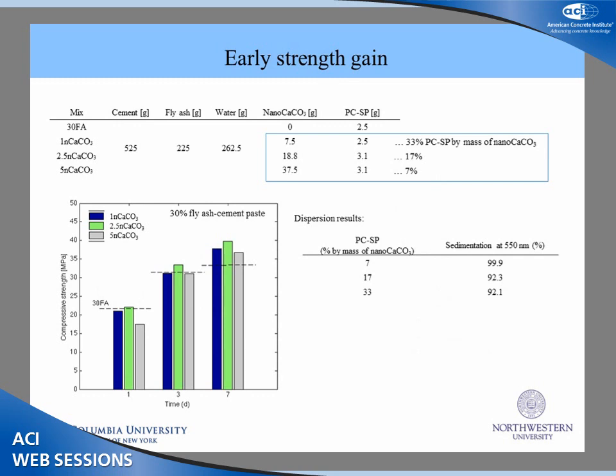Now we also tested early age strength gains, so 1, 3, and 7 day. If you just focus on this plot in the lower left-hand corner, the line indicates just 30% fly ash cement paste with no nanocalcium carbonate. And then the effect of 1, 2.5, and then 5% nanocalcium carbonate addition. And we see that by 7 day, the 2.5 does exhibit an increase in strength by about 20%. So we are seeing an improvement. And there's also an improvement even at 1% as well. But if we look at the 5%, there's some erratic behavior where at 1 day, it exhibits a lower strength than the control. And at 7 day, there is an improvement, but it's less than the 2.5. And this can be explained by issues of dispersion.